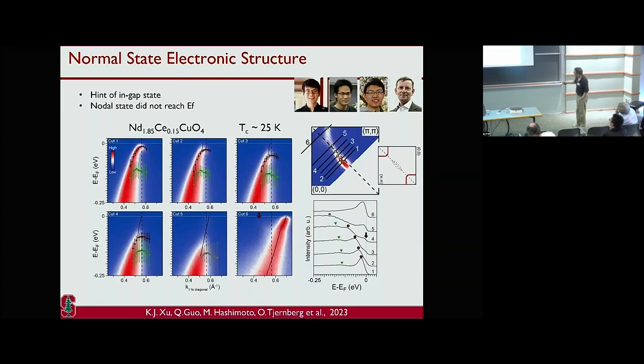Now, it's immediately clear that in this spectra, at this point, you can see there's a huge spectral suppression. In other words, the antiferromagnetic band bends back 100-some millivolts below the Fermi level. Okay, that's this red feature. Okay, ignore the green for the purpose of this talk. That's the antiferromagnetic reconstructed Fermi surface. Then you notice that, in fact, there's a residual spectral weight inside the magnetic gap, okay, in this region. And if you trace it out, in other words, the band structure has two pieces: there's a higher energy antiferromagnetic band gap, and there's a residual state. The question will be, is this residual state just trivial disorder? It can also give that to you. That will be the test.